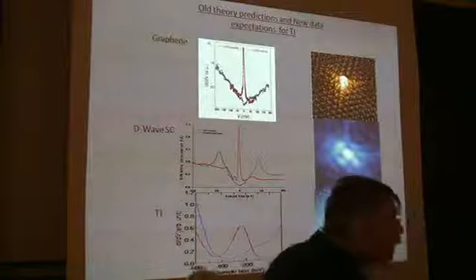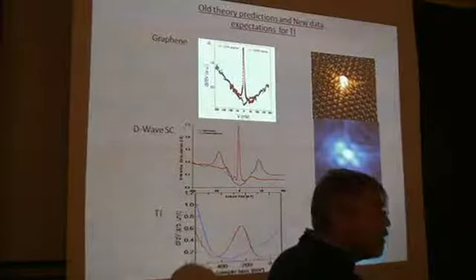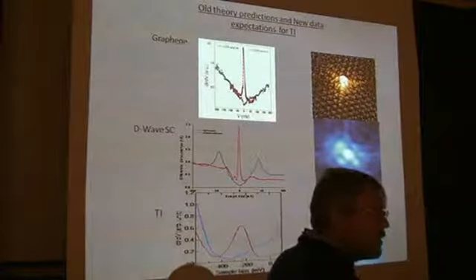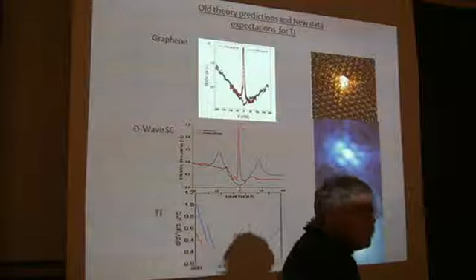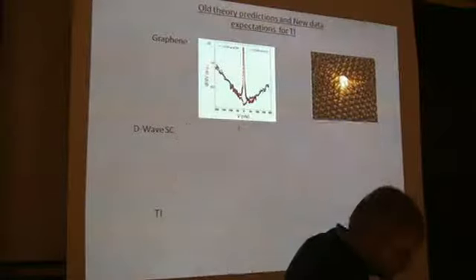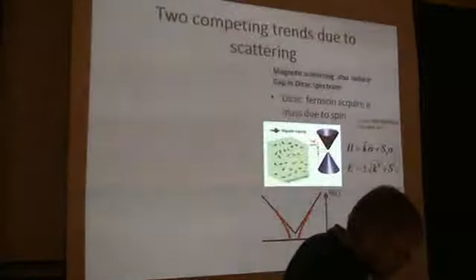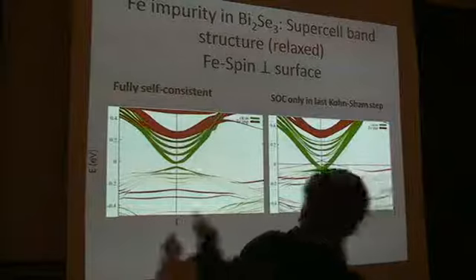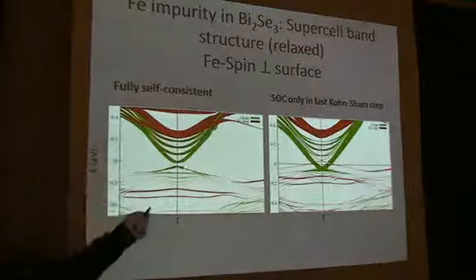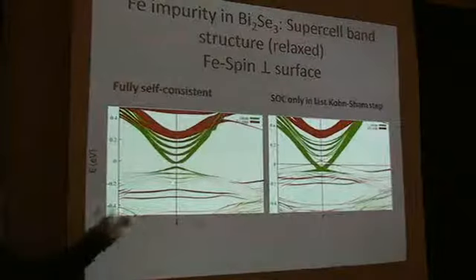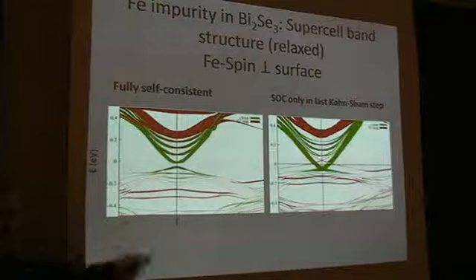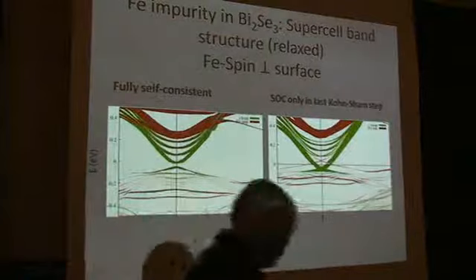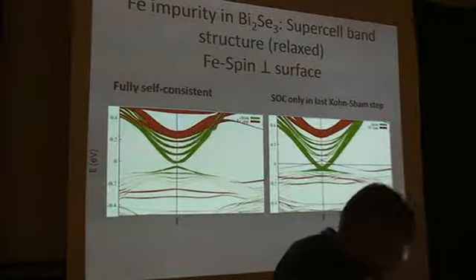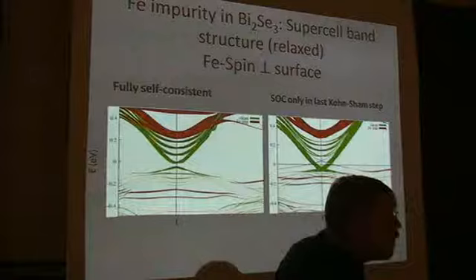Why is the blue line so asymmetric in the topological insulator? Take a look at the tunneling data there. It's because basically there is no particle-hole symmetry. Even in the band structure, you can see that the filled states, let me show you, the filled states have less of a dispersion. Effectively, it means that they have a larger density of states. Only if you come close enough, it does have particle-hole symmetry.